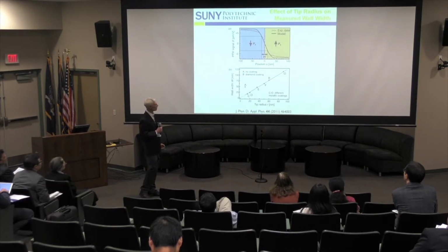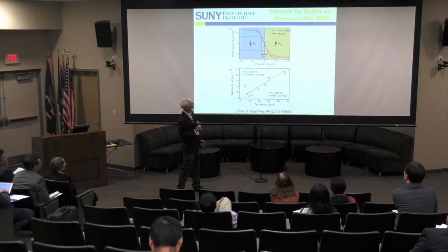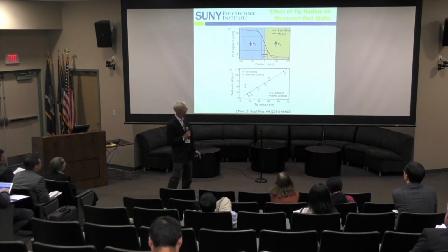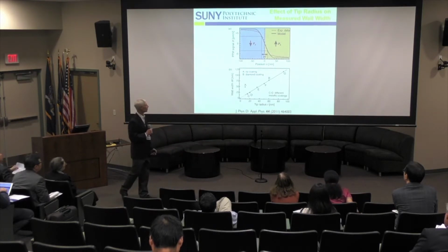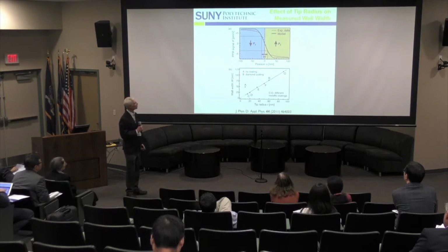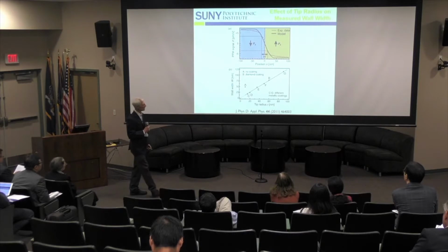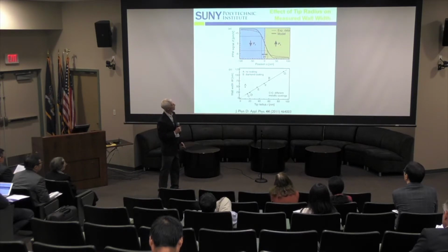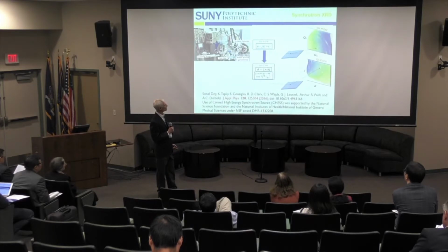You can even determine something in the same paper about the width of the transition between up and down polarization based on the width of the probe tip. And so, of course, the bigger the probe tip, the wider the width of that transition that you're going to measure or observe. So there's some importance in understanding your probe tip if you're going to do these kinds of measurements.